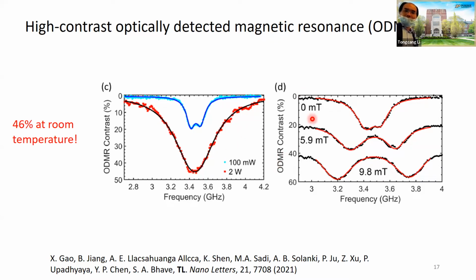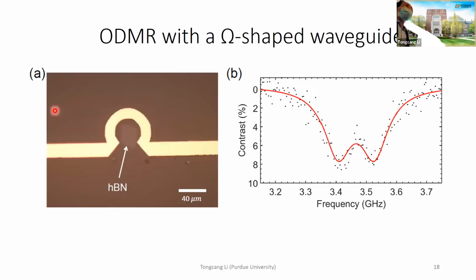And also, we measured ODMR as a function of magnetic field. Does that mean the dark state is perfectly dark? It should be very dark. Yeah. I see. I guess this emission is pretty weak, so the dark state is even weaker. So this is even higher than the diamond emitter contrast at room temperature. We also did a test with a different omega-shaped waveguide, which people typically use for diamond emitters. We drive with even higher power, and we get a few percent, but much weaker than the 46% we observe.